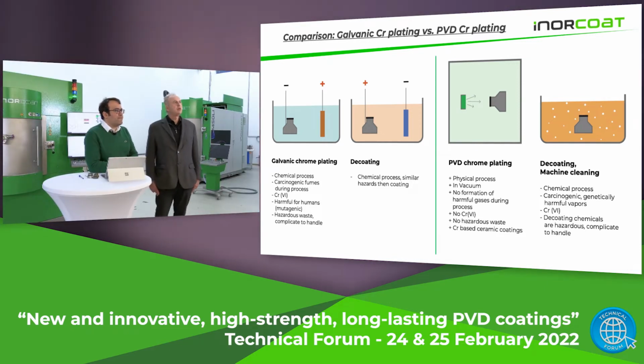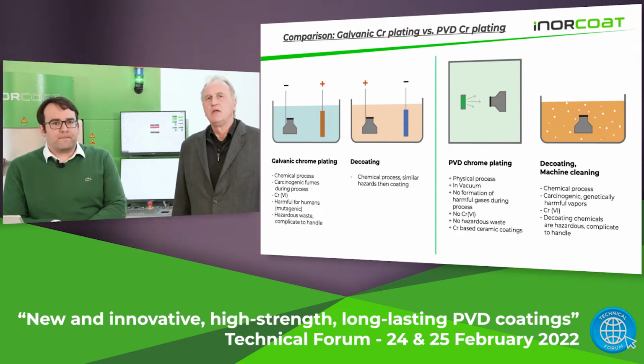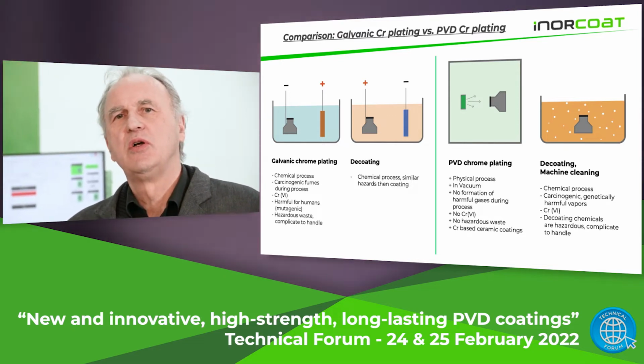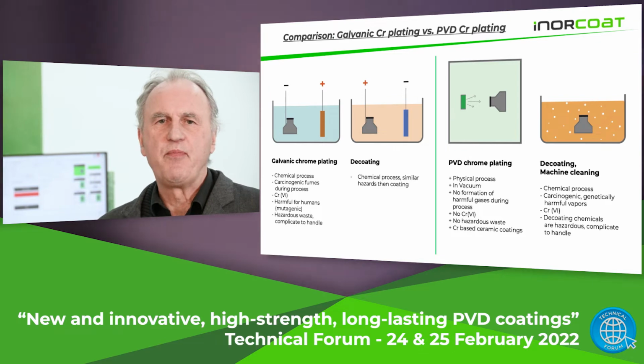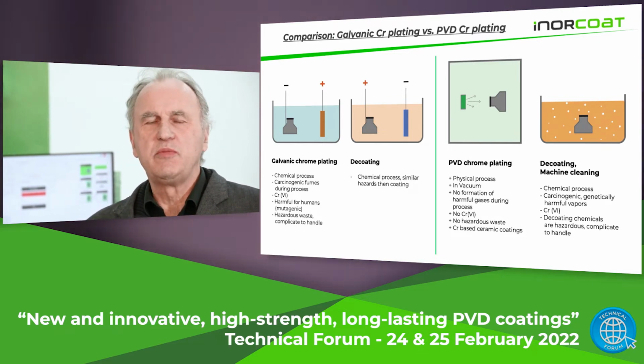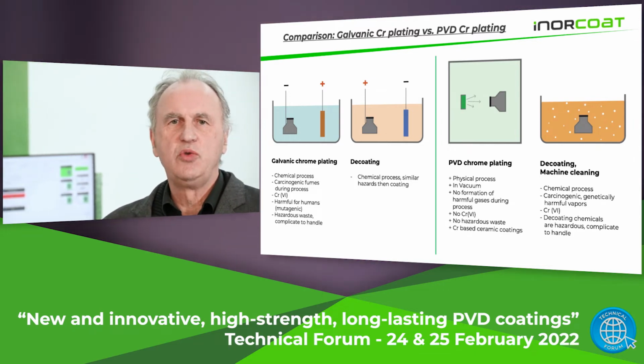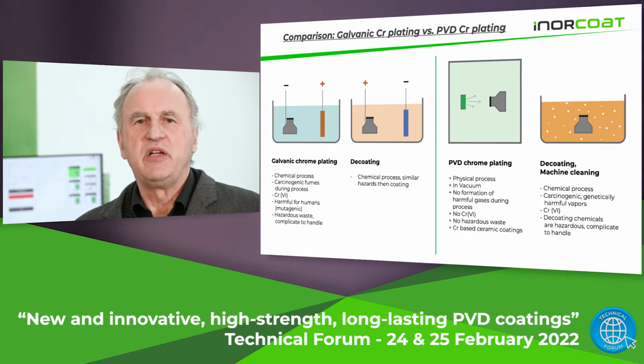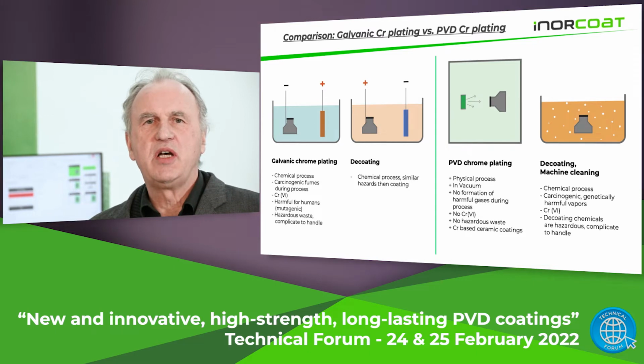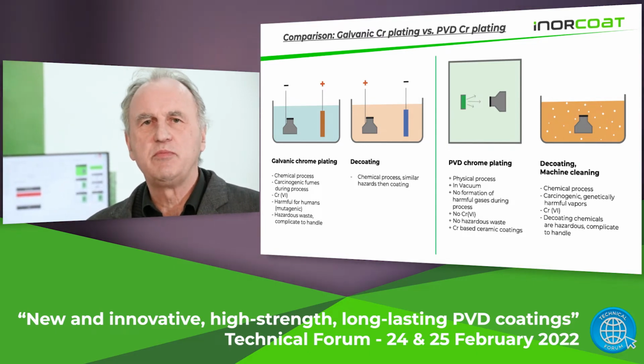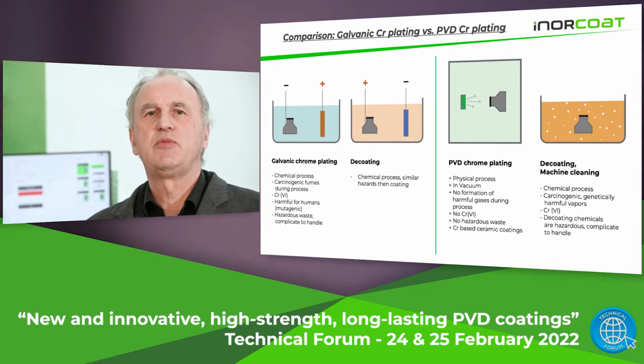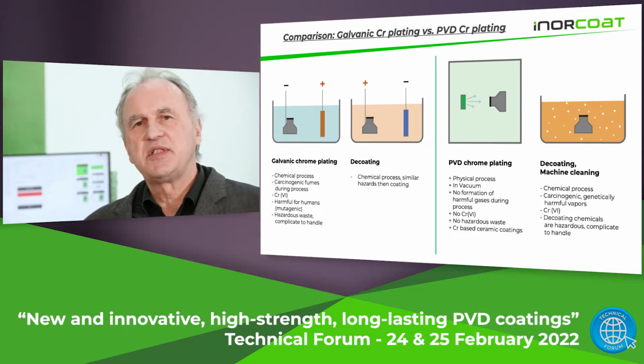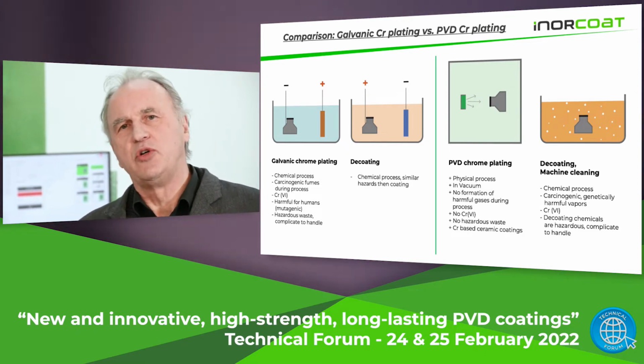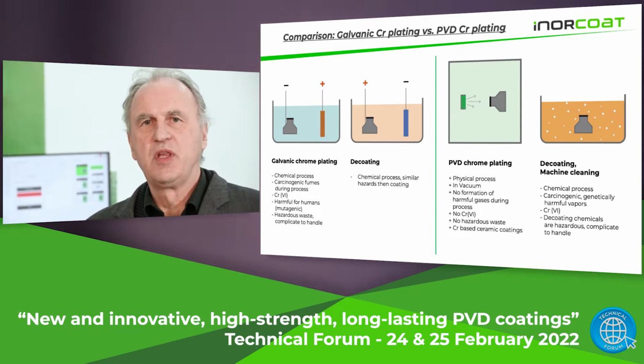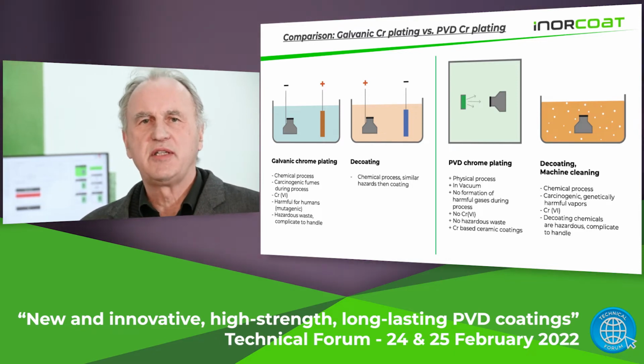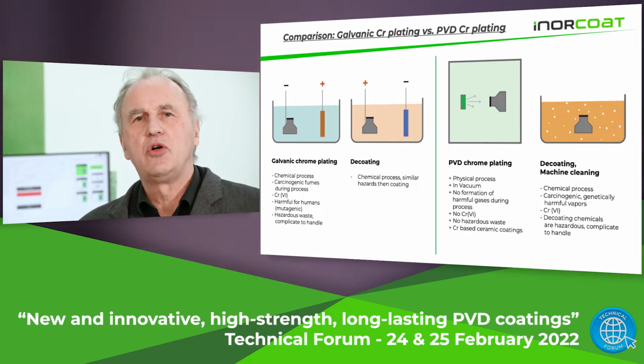PVD coatings, which means coatings which are deposited in vacuum, are generally used in the form of chromium or chromium alloy ceramics. This chromium deposition occurs in vacuum without any use of hexavalent chromium and is therefore environmentally okay. Nevertheless, we coat also the substrate holder, we coat other machine parts, and those machine parts need to be decoated from time to time. And during the decoating process, if it's chemical decoating process, there might occur, just as described before, the hexavalent chromium. Therefore, since PVD coating is a very versatile technique, we develop chromium-free coatings.